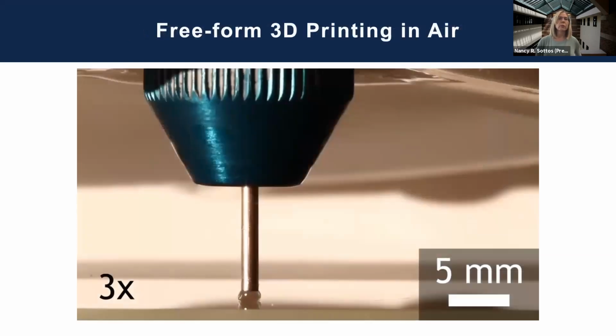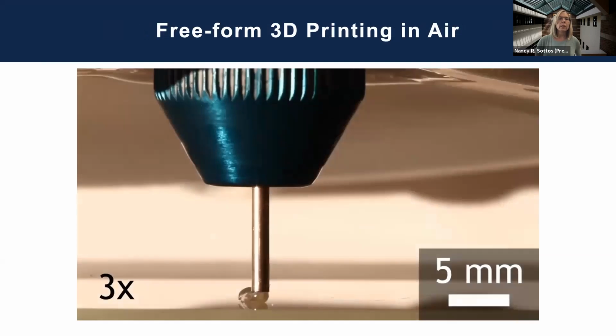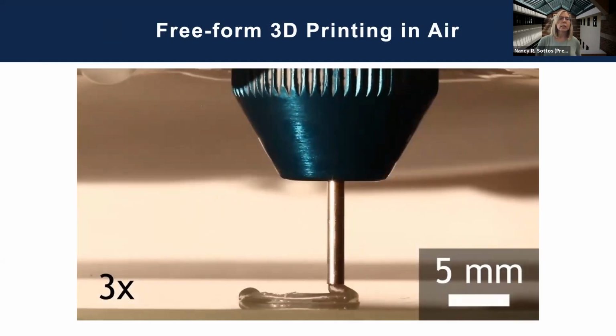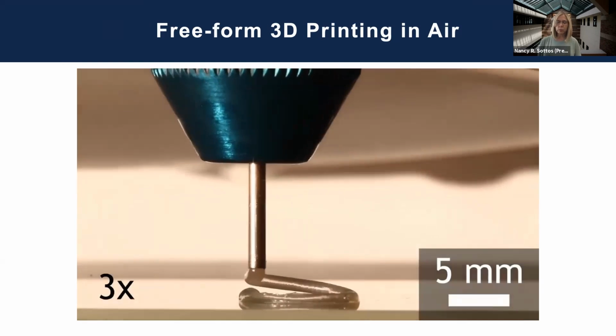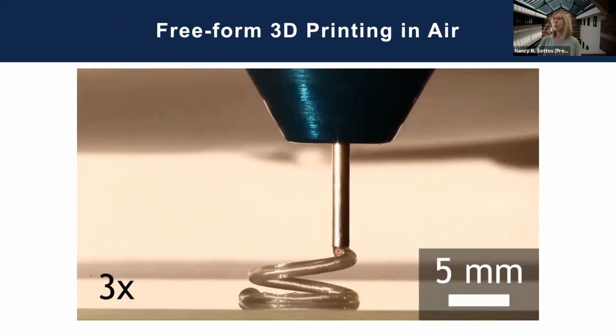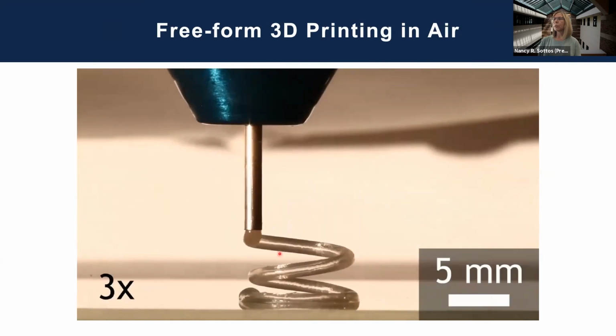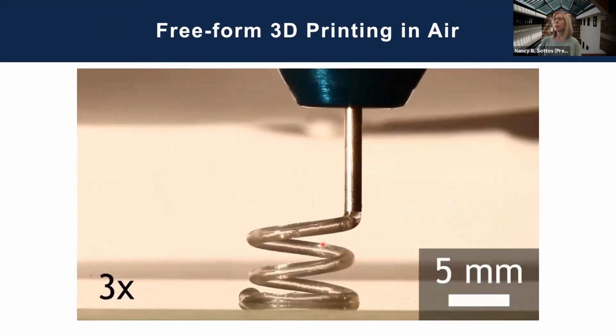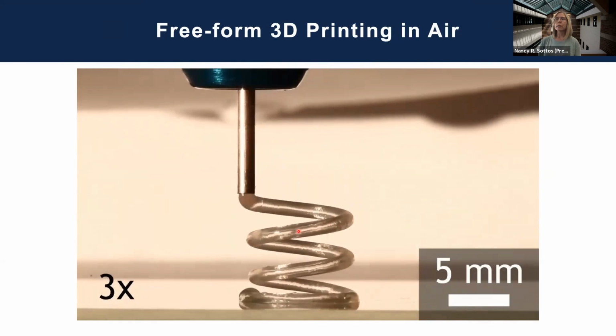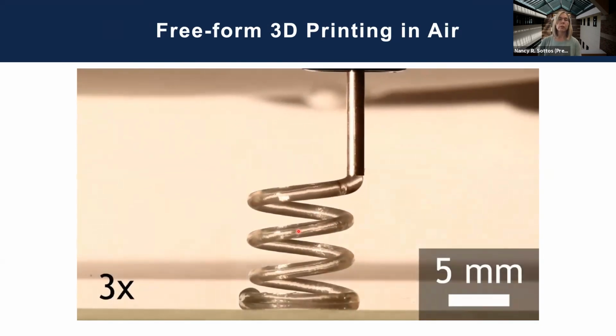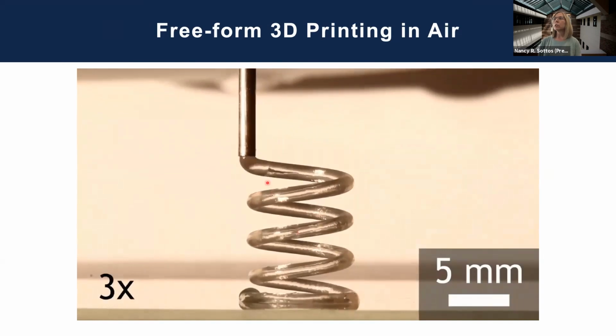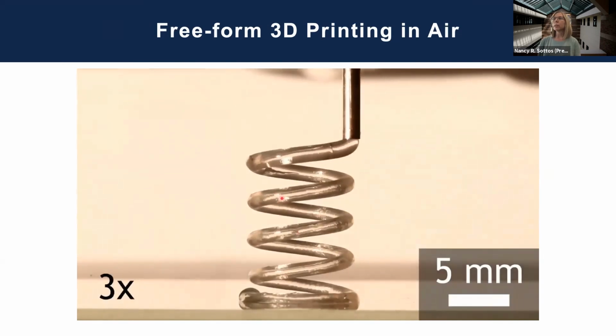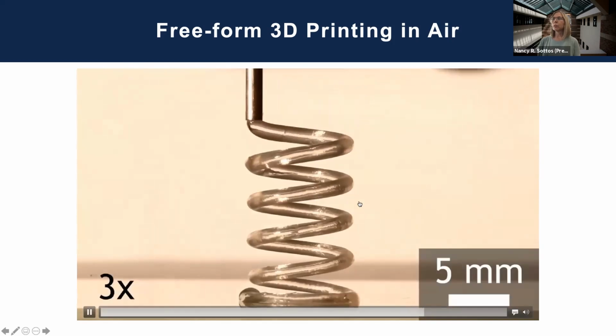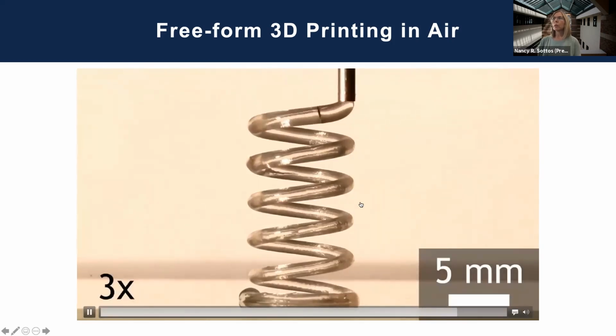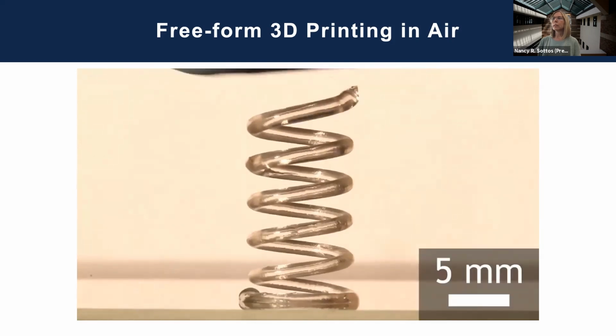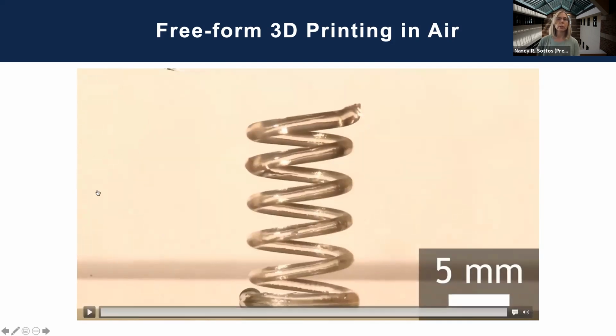And so I'm going to show an example of a freeform 3D printing in air. And so this has been triggered on the heated print bed. And as this cycles up, you can see the front here chasing the print head as it goes through this freeform spiral. And everything behind the front is a cured thermoset polymer, again with a TG of 160. And it's just gel in that small segment close to the print head. You see this video will finish soon. And when it completes, you can see it's fully cured thermoset. There's no secondary curing necessary.